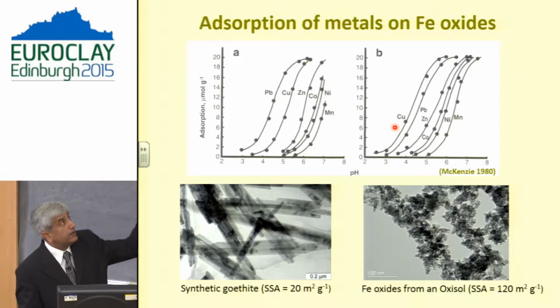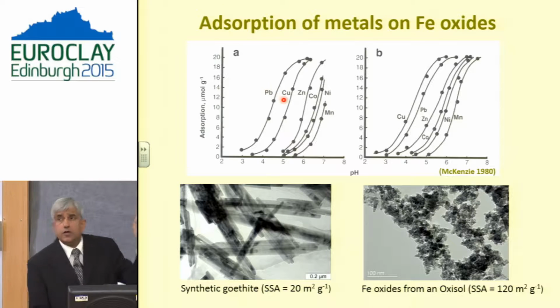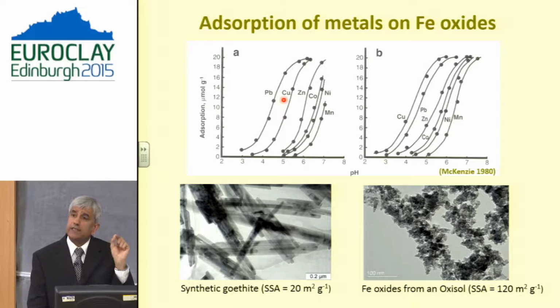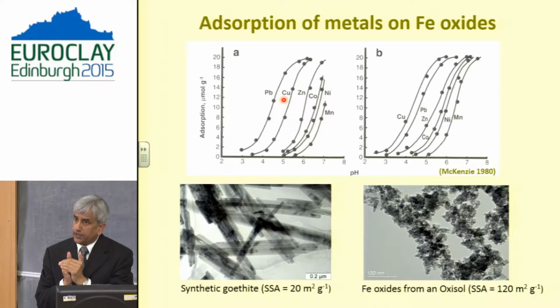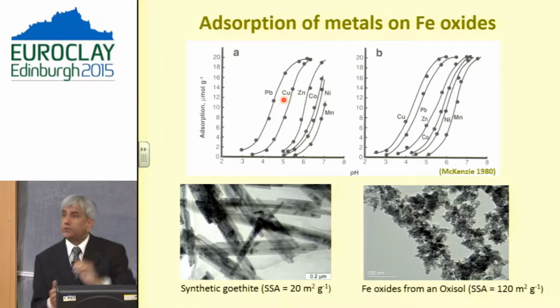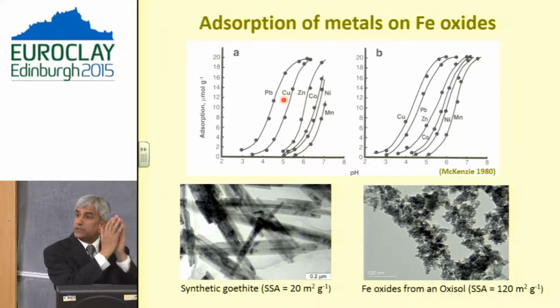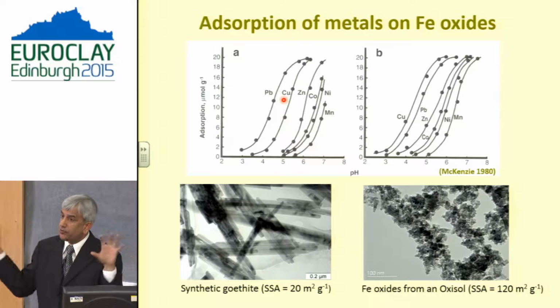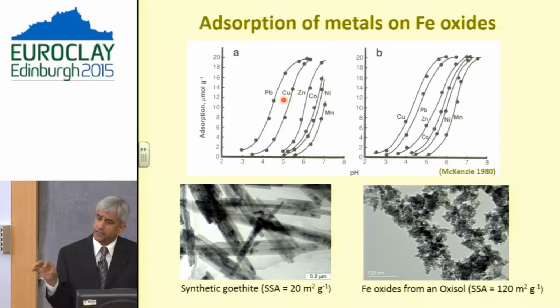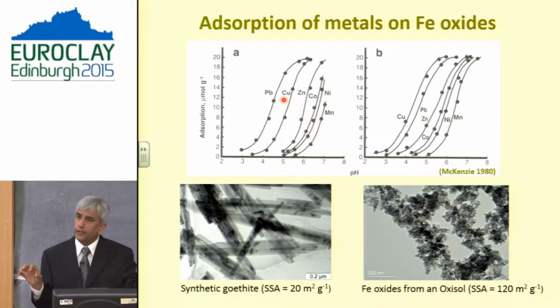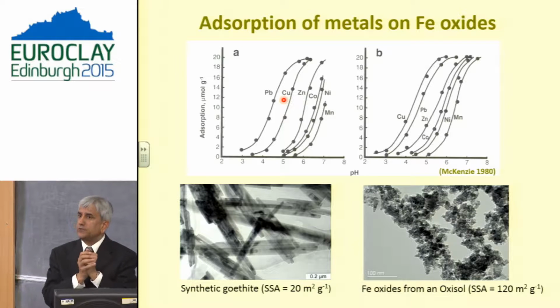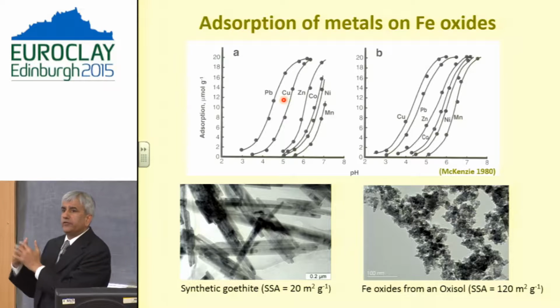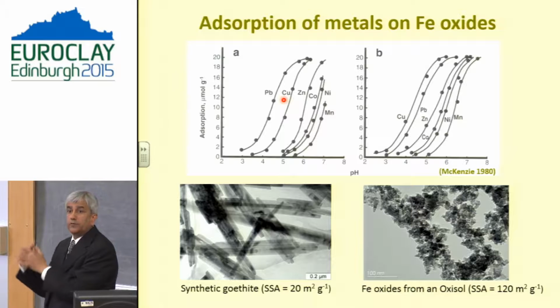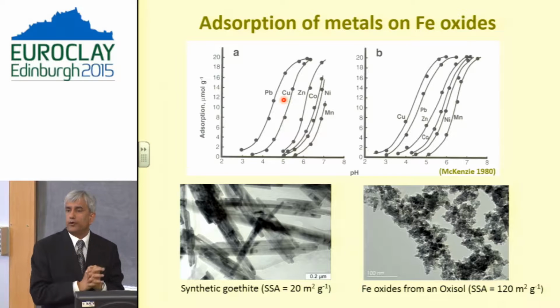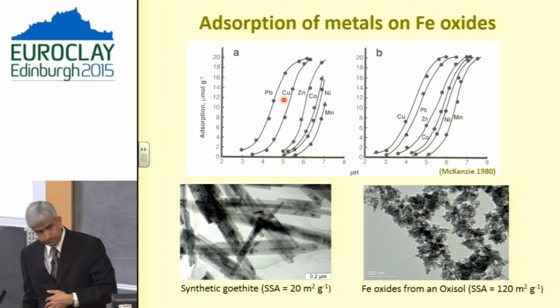And one thing which is different here is remembering that copper and lead were not getting in the structure of goethite. When you look at the adsorption behavior, they are the ones which are adsorbed most compared to the other elements. So there are two clear separations here: elements such as copper and lead are adsorbed on the surfaces, whereas elements such as zinc, cadmium, chromium are more incorporated in the structure of iron oxides.